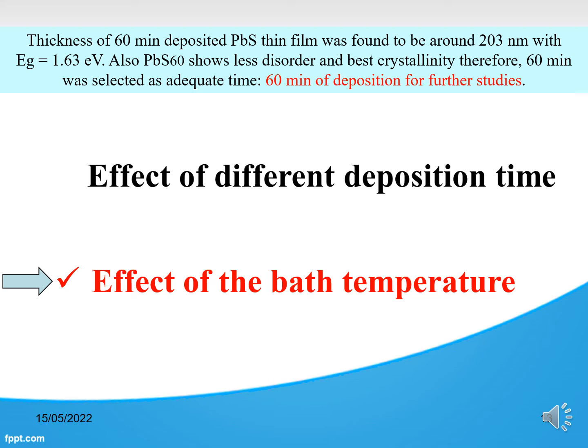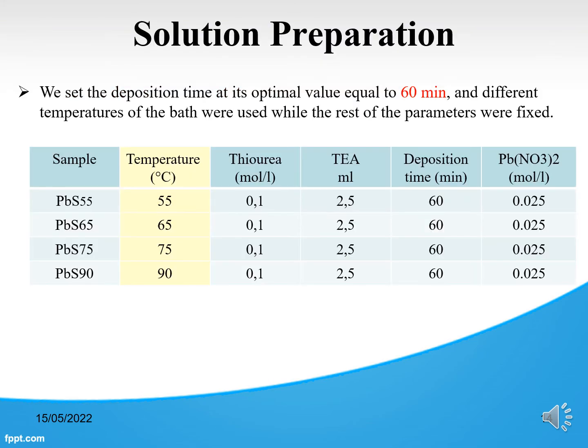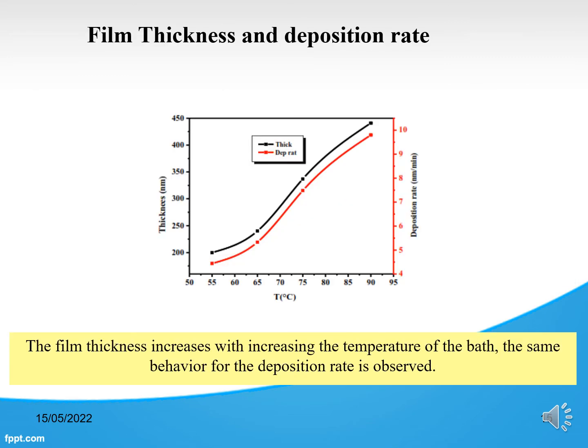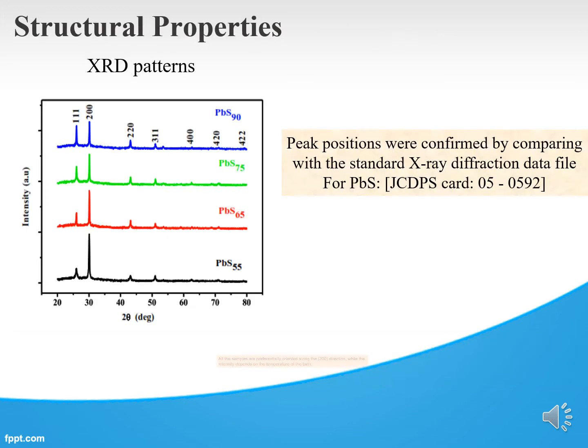The effect of the bath temperature. For the solution preparation, we set the deposition time at its optimal value equal to 60 minutes, and different temperatures of the bath were used while the rest of the parameters were fixed. Film thickness and deposition rate. The film thickness increases with increasing the temperature of the bath. The same behavior is observed for the deposition rate.